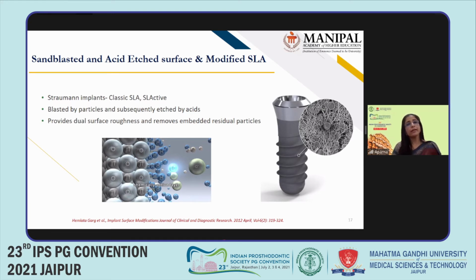Researchers have also tried to improve the hydrophilicity of these conventional SLA implants, and they came up with the modified SLA implants, which were introduced as the SLActive implants. So how is this done? They rinsed the SLA implant in a nitrogen atmosphere and stored it in a saline solution until installation. This is supposed to reduce the carbon contamination, and it also improved the hydrophilicity of the implant. This procedure allows SLActive to maintain a very chemically active surface, which is conditioned to the human body.